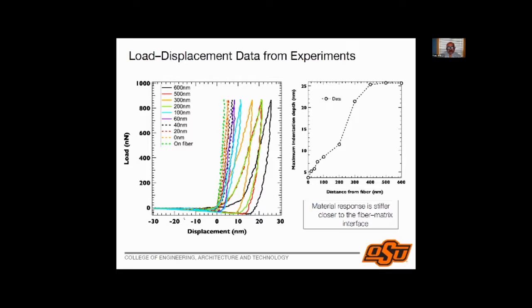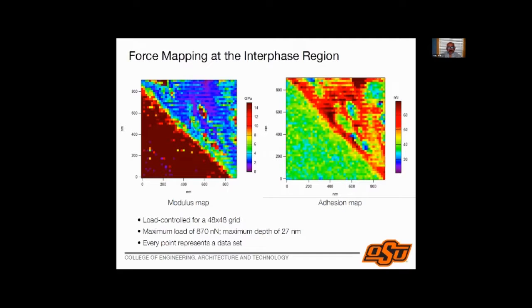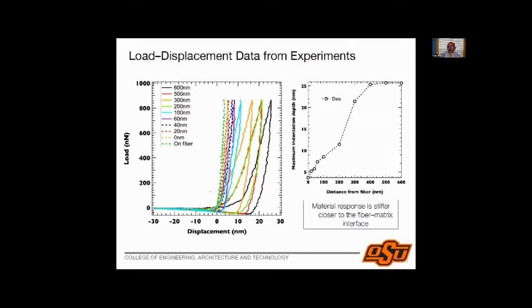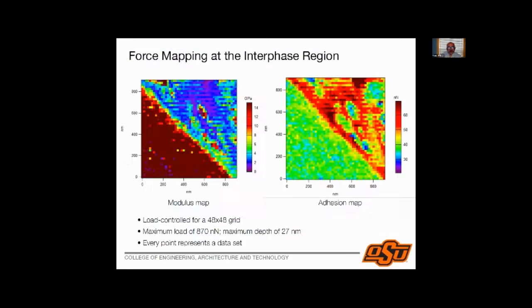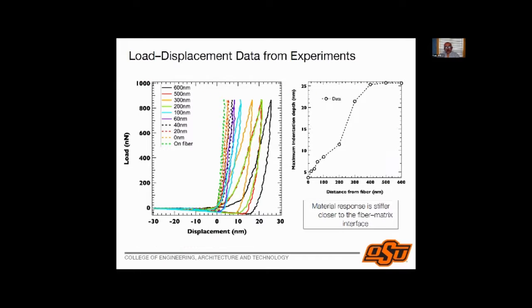So these are load versus displacement curves that we get from each one of those data sets. So I can go over here, and from each one of these data sets, I can pull out a load versus unloading curve. So that is the amount of data that is represented. If I can do it for every point, then I can do it as a function of distance from the fiber. So I start plotting load displacement as a function of how far from the fiber I am. This black solid line over here, the last one, is 600 nanometers away from the fiber. And then I keep coming closer and closer, and the green one is right on the fiber, and these ones are right in the interface region. So I can get these load displacement curves. From these load displacement curves, I can get different things. For example, I can look at maximum indentation depth and so forth, and I can get the modulus.